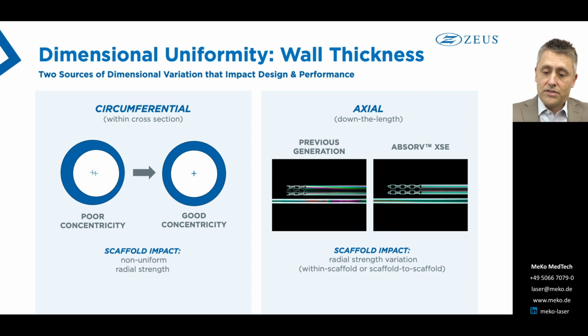Now, down the length variation can occur when the average wall thickness varies as you move down the length, and that can cause either within scaffold or scaffold to scaffold radial strength variation. And this is really where our new platform shines. If you look at these polarized images on the right there, you can see the major improvements in down the length uniformity with Absorv XSE on the right compared to a previous generation tubing. It's really easy to see in those polarized images. And this really is a game changer. This is something that we are really excited about, and it's going to do a lot for the markets.